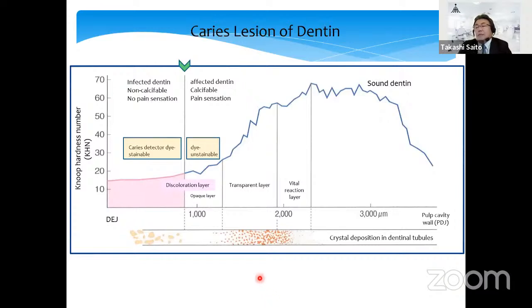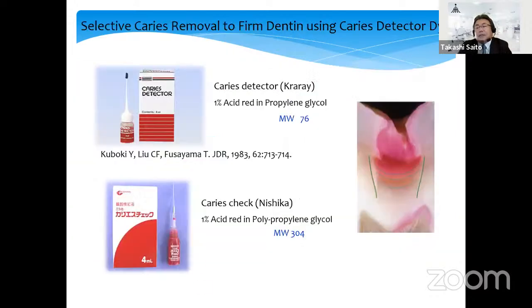So Professor Fusayama at TMDU developed the caries detector dye that can stain only the infected dentin in 1983. In Japan, the caries detector dye is recognized as the most reliable because the dye infiltrates moderately into the collapsed dentin structure by decalcification. The dye is acid red. The molecular weight of the solvent, propylene glycol or polypropylene glycol, regulates its infiltration into the exposed collagen network in infected dentin. It is used for careful caries removal to avoid unnecessary cutting.